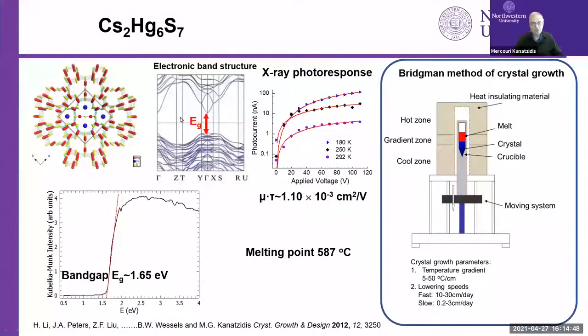So let's look at this one. Here's the structure. It's an open crystal structure that has mercury and sulfur. That's heavy. It also has cesium in tunnels in the structure. It's a direct band gap material of 1.65 eV. And it actually does have strong photocurrent, that you see here, applied voltage versus photocurrent. We have a nice response. And therefore, we did some more work on this.